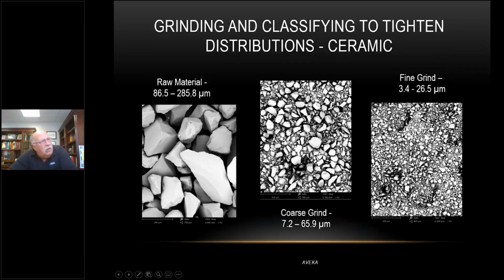So what we have here, this is the raw material. It had a D10 to D90 of about 200 microns, 86 to 285 microns, big particles. After our first grind on this stuff, on that coarse grind, where we're doing the low rotor speed, we got a particle distribution of, I believe it was 34 microns, and the distribution went from 7.2 up to 65.9. If we go to the finer grind, where it's a higher rotor speed, so we're classifying, we're doing more grinding on this system, you can see the particles have gotten smaller, but look at all those fines that are in there. I mean, it's an incredible amount of fines.